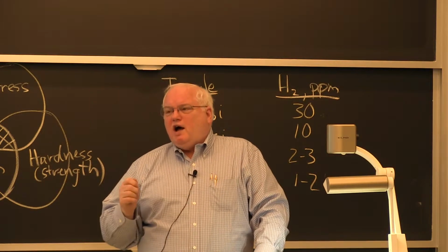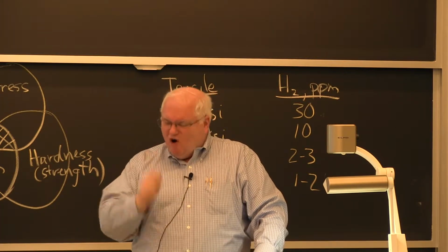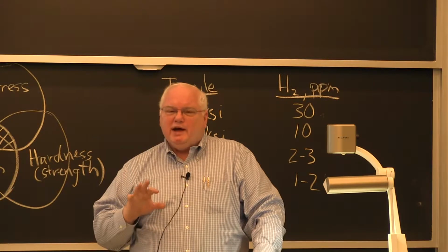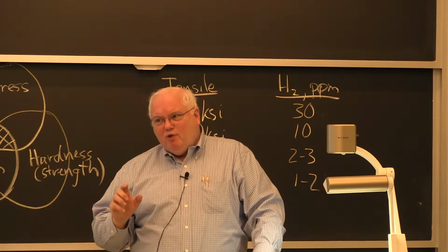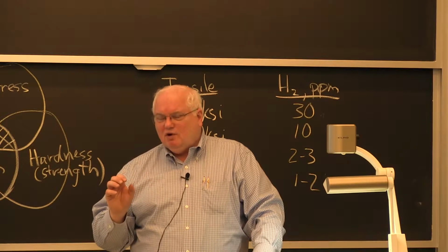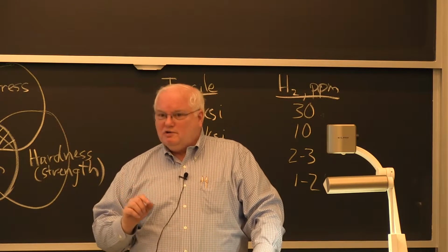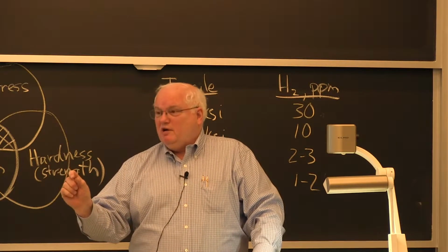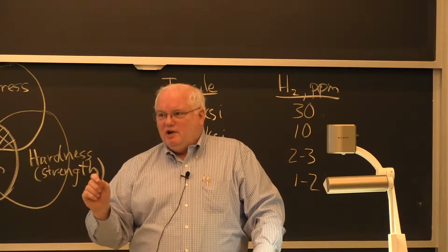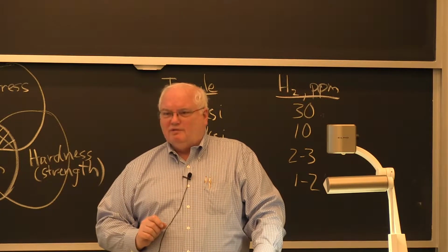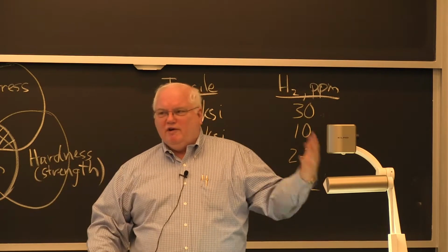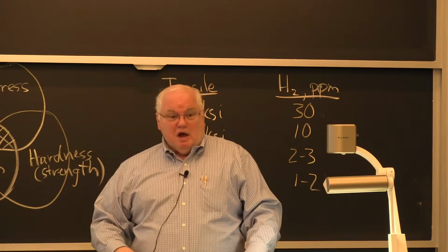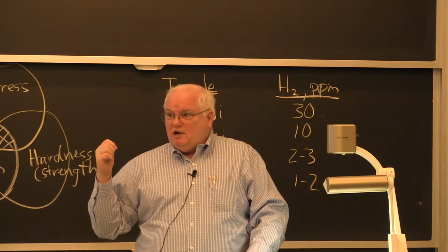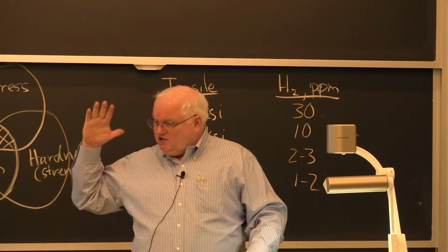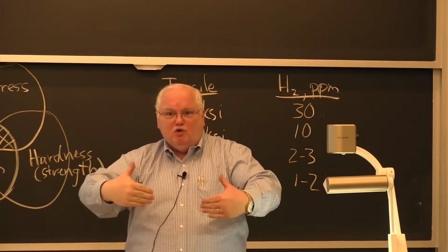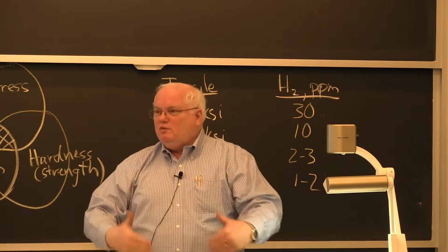The other one is, it turns out, it used to be 10 years ago, shipbuilding was by far the most precise. Turns out, semiconductors, when I'm getting down to 14 nanometers over a centimeter, you start figuring that out, and you're getting to just a little bit better than shipbuilding now. You have to go on the extremes, very small or very large, to get the most precise tolerance. In a shipyard, they have to worry about when the sun comes out from behind the clouds, because the heat on that side of the ship will cause the whole ship to bow when they're building the ship, and the distortion will.